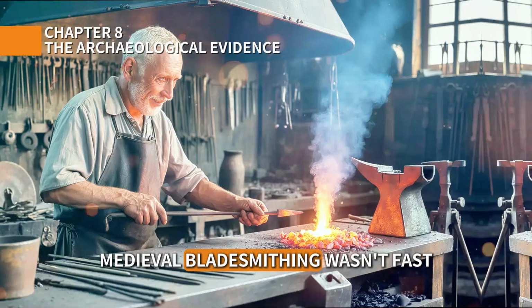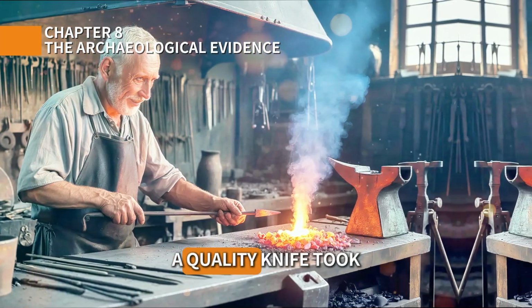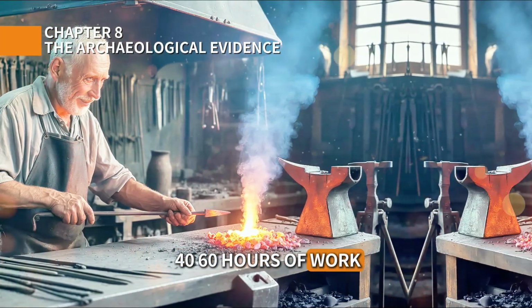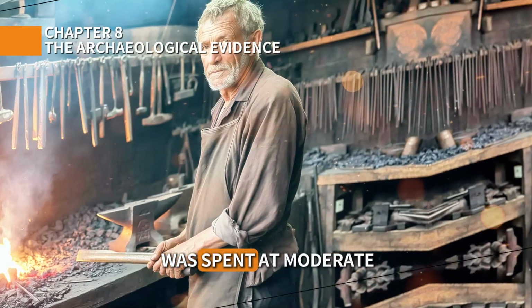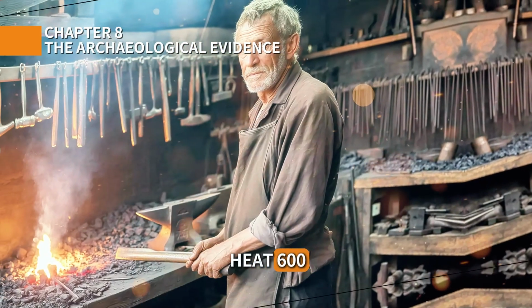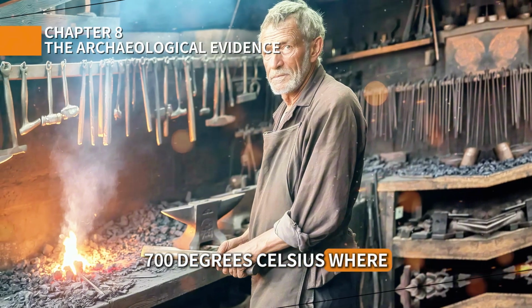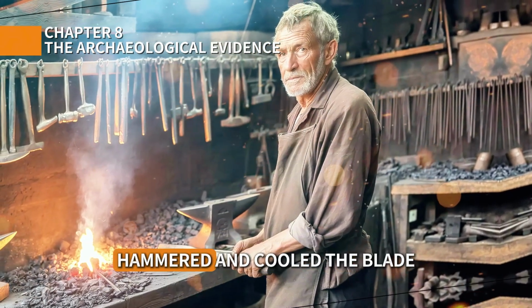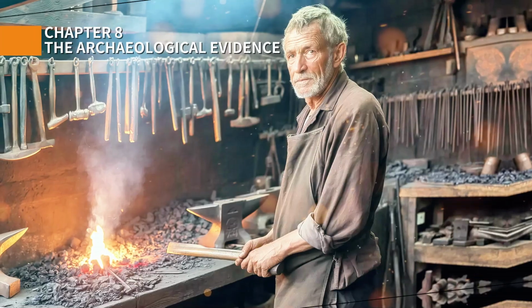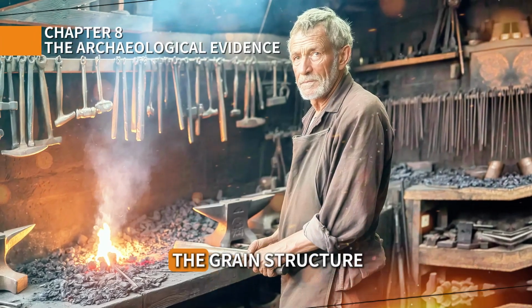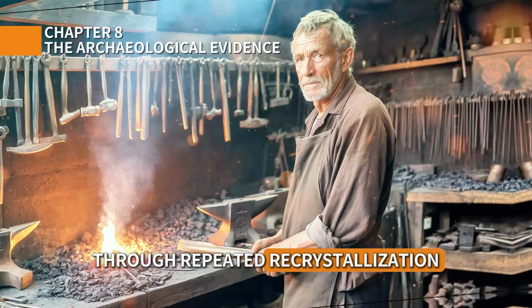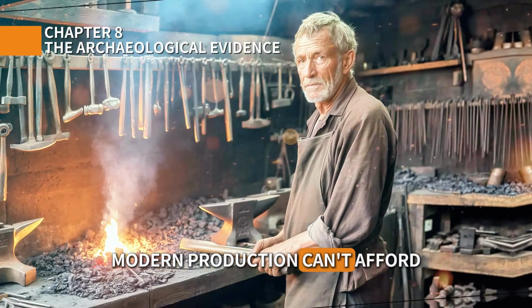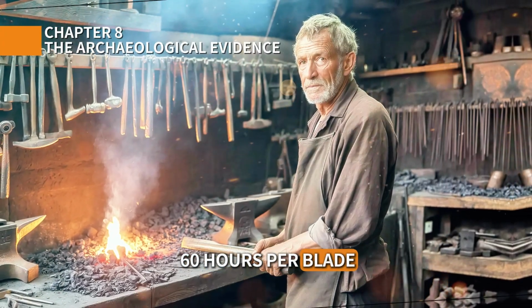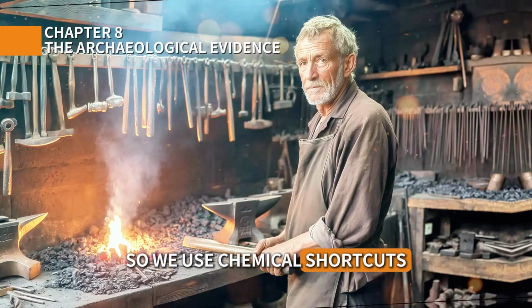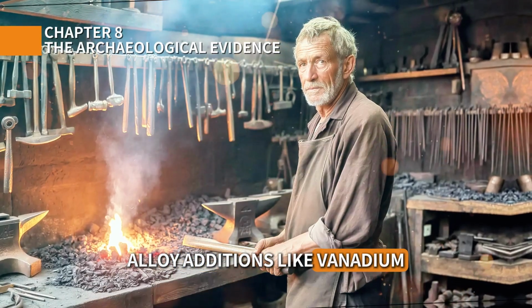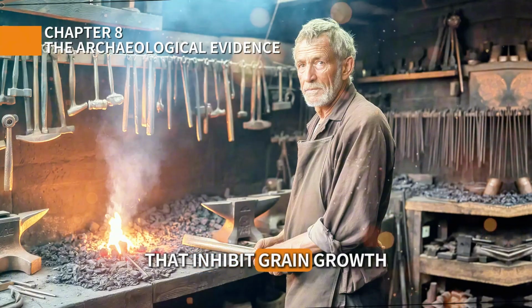Medieval bladesmithing wasn't fast. A quality knife took 40–60 hours of work. Much of that time was spent at moderate heat, 600–700 degrees Celsius, where the smith repeatedly heated, hammered, and cooled the blade. This thermal cycling refined the grain structure through repeated recrystallization. Modern production can't afford 60 hours per blade, so we use chemical shortcuts, alloy additions, like vanadium and molybdenum that inhibit grain growth.